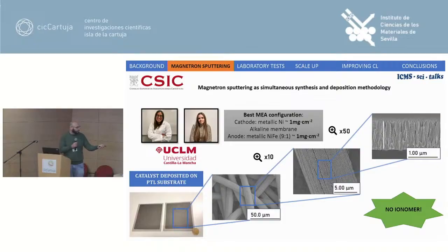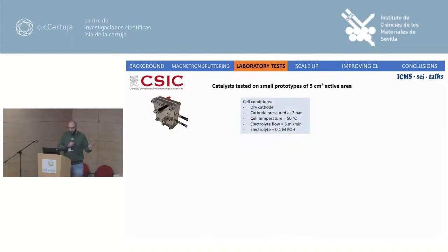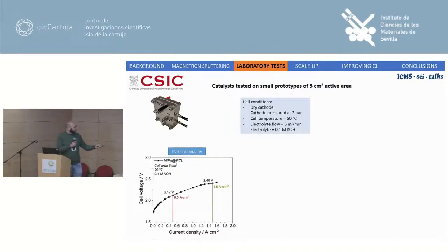In our case, this is not necessary, so we simplify the deposition procedure, and we also avoid possible degradation that is promoted for this kind of molecules, which are normally not stable in alkaline media. So if we use this combination of cathode and anode in a small prototype water electrolyzer of 5 square centimeters of area, we can see the performance by comparing the voltage response at different current densities.